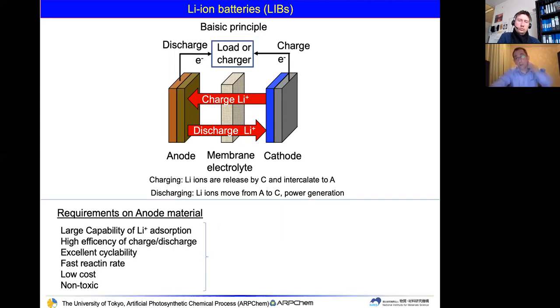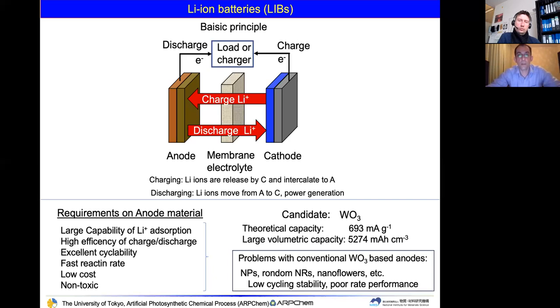However, there are requirements on the anode material. The anode material should have large capability of lithium absorption, high efficiency of charge and discharge, excellent cyclability, fast reaction rate, low cost, and of course it should be a non-toxic material. So one of the good candidates is again tungsten oxide, because the theoretical capacity is around 700 milliamp hour per gram, with quite a large volumetric capacity, which is around 5,270 milliamp hour per cubic centimeter.